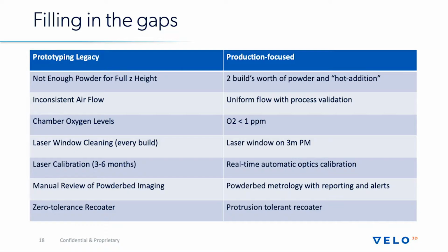Laser window cleaning is much less frequent than what you see in current systems, while laser calibration is much more frequent than what you get in conventional systems due to the automated nature of that. The powder bed imaging, one of the most interesting metrologies that we have, is essentially a 3D scan of the powder bed. So I can report out every layer what's really going on with the powder bed, the quality, the protrusions that you might be seeing. If there's supports that are failing, the system will measure those and actually give you a quantitative measurement of that and not allow the recoater to smash into it, which is a nice feature.